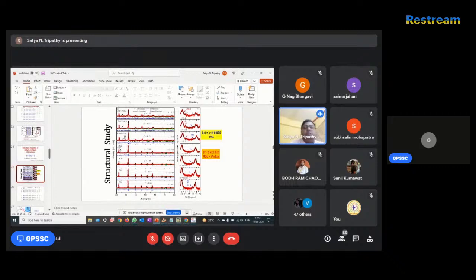As per the similar explanation I gave you, because dysprosium will go to the bismuth site, it will create a chemical pressure, and the XRD patterns are similar to the parent structure. So we take the R3C space group. After that, new reflections are coming, and that is a part of DyMnO3. So we use the Pna21 space group. We could have used Pnma, but this structure is non-centrosymmetric. We obtained a ferroelectric hysteresis loop, so we did not use Pnma because of the non-centrosymmetric nature.